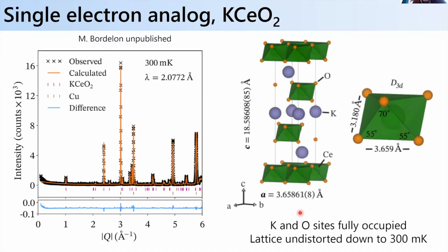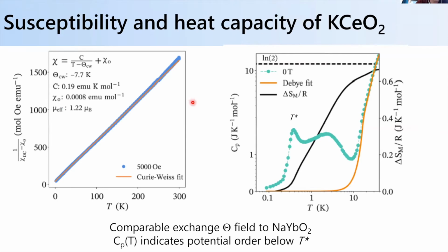But one thing we wanted to look at was, okay, fine, let's look at the cerium compound. And so this is the same structure, and we can do the same type of approach. We can do neutron diffraction, and we can show that the potassium and oxygen sites are fully occupied, which is important, especially for this system, because it doesn't really want to stay stable in air. So we have to be very careful. And the lattice stays more or less undistorted within resolution down to helium-3 temperatures. So it still has this perfect triangular lattice symmetry.